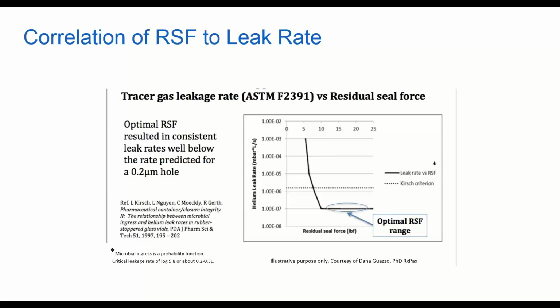We need to do a little bit more, and at room temperature, oftentimes what we want to do is look at the effect of residual seal force, seal tightness, on some type of helium or some type of leak rate. In this example, helium is used, and this and many other studies have shown that as residual seal force increases, leak rate decreases. And at some point, you're going to go beyond your ability to measure that change, and you're going to get to essentially leak rate cutoff.